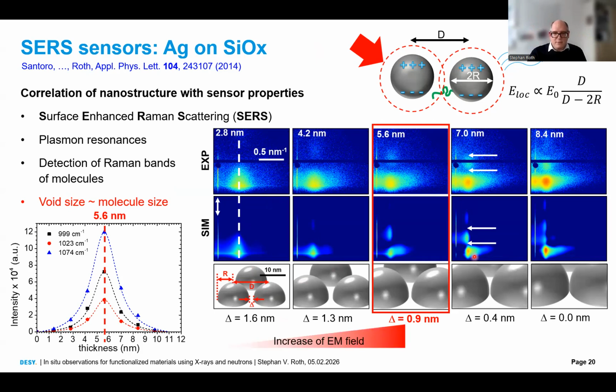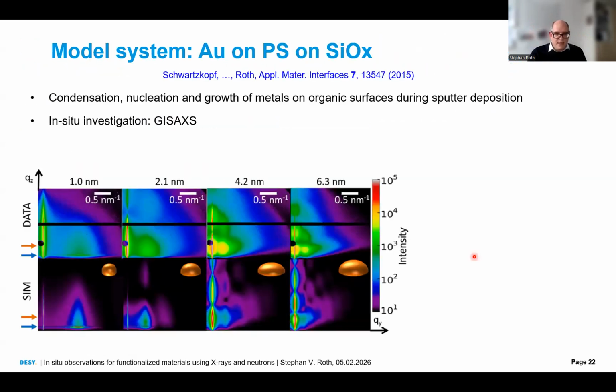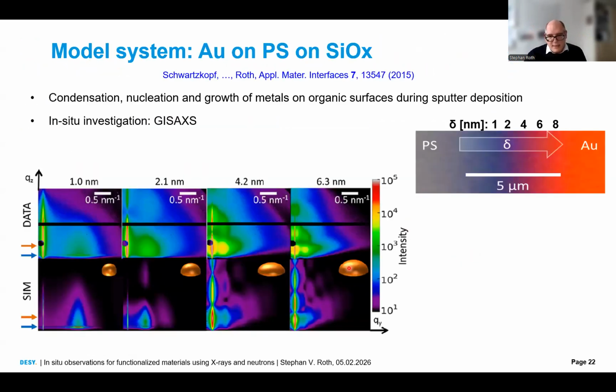And this is what we did then in the next part here. You see here the changes in the GISAXS pattern, and we assumed a different shape. And this shape then you can optimize and you can really fit this to the scattering pattern, based on features like the position of the side maximum here, this structure here, and this structure here close to the middle of the detector.